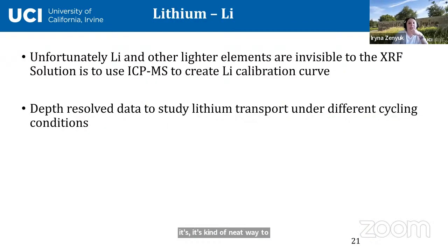But for lithium, the problem obviously is that hard X-rays are insensitive to lithium. We cannot detect it using X-ray fluorescence, for example. So obviously ICP-MS must be used to calibrate lithium curves. And the goal, as I mentioned already, is to use that result in GDOES to study lithium distribution under different cycling conditions.